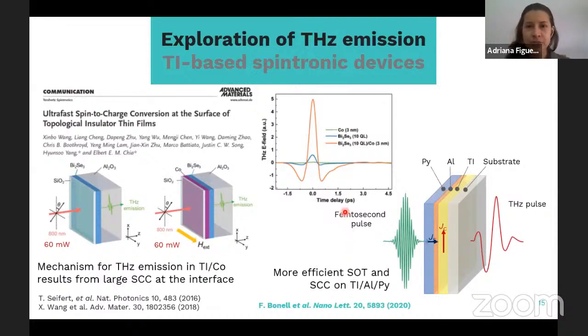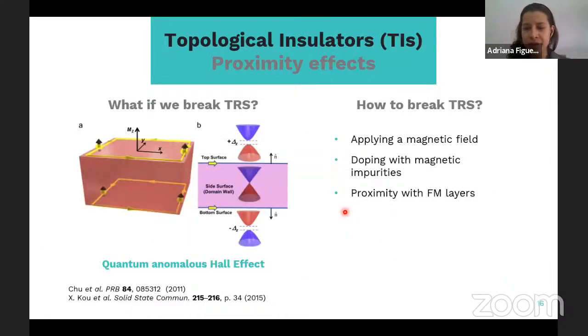Okay, so this is in terms of metallic ferromagnets, but we can also study more proximity effects of the TIs with non-metallic ferromagnets, with insulating layers. And why is that? We want to study more proximity effects because we want to break time reversal symmetry in the TI, in order to introduce ferromagnetic order in that material, so that we can observe novel phenomena such as the quantum anomalous Hall effect.